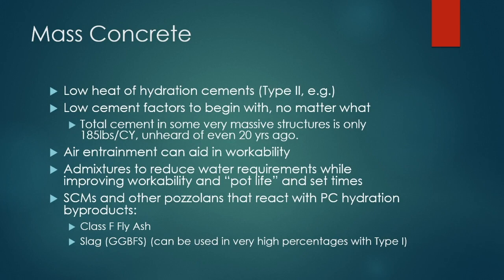So some of the other considerations: obviously you need a low heat of hydration cement, for example, like a Type II. It's pretty rare that people are using a standard Type I cement these days, unless you have a very high percentage of slag. And I'll talk about that in a minute. One of the things that they stress in the 207 document is that mass concrete mix designs typically have very low cement factors to begin with. Some of them are ridiculously low. There was one that they cited in the document where it was 185 pounds of total cementitious materials per cubic yard, which is unheard of even as recently as 20 years ago. So there have been a lot of advances made in even the past 10 years in understanding the effects of these cementitious materials.